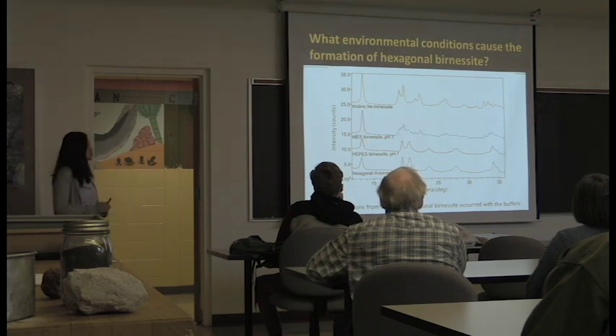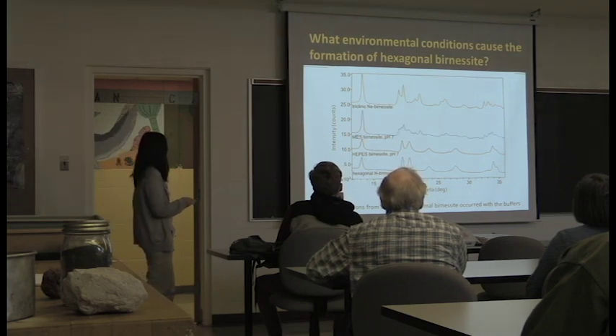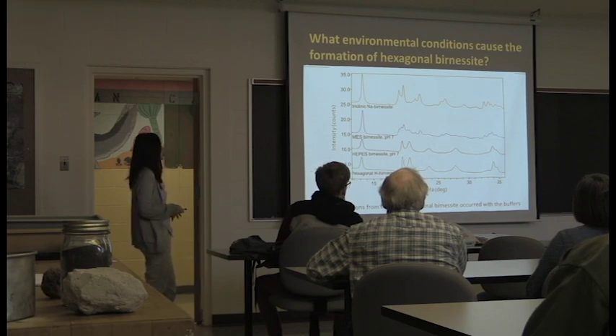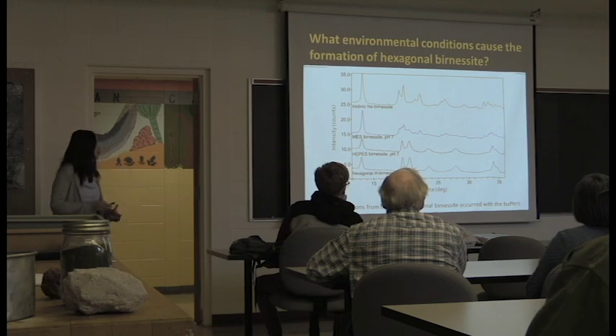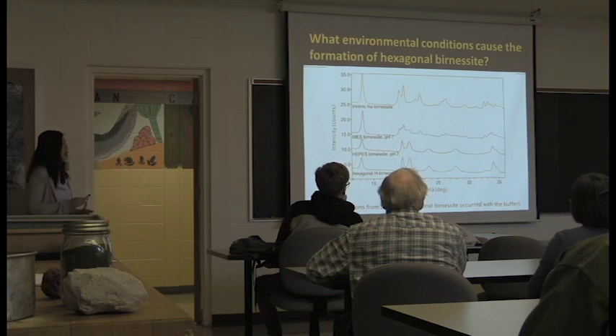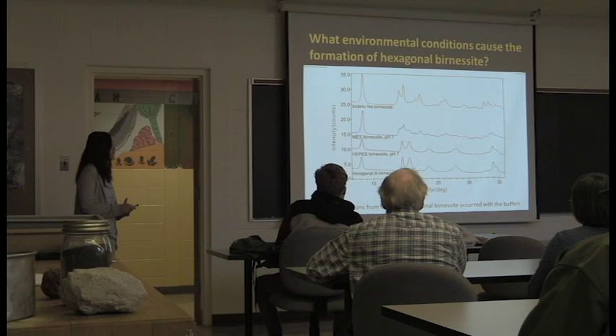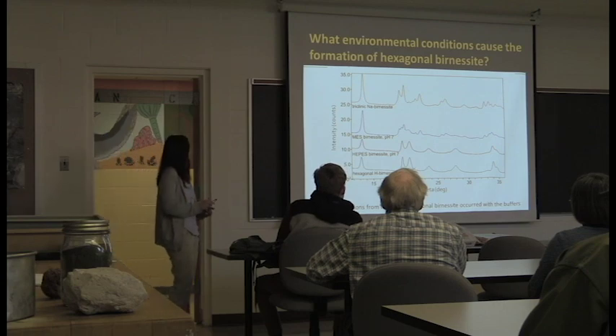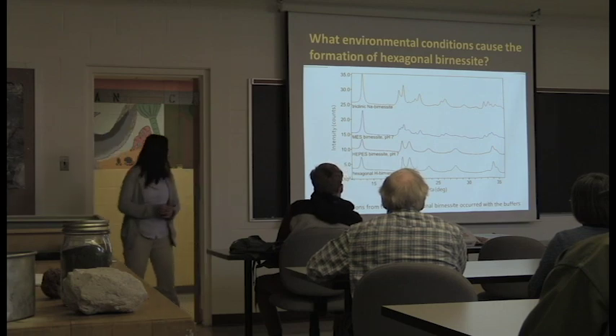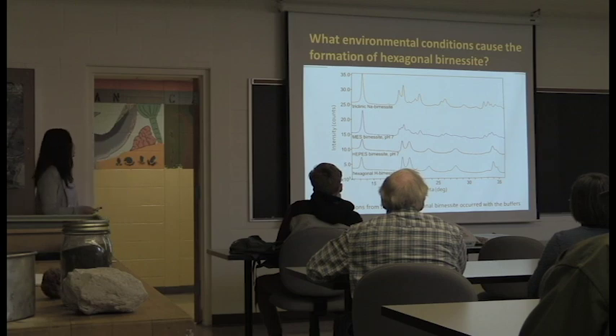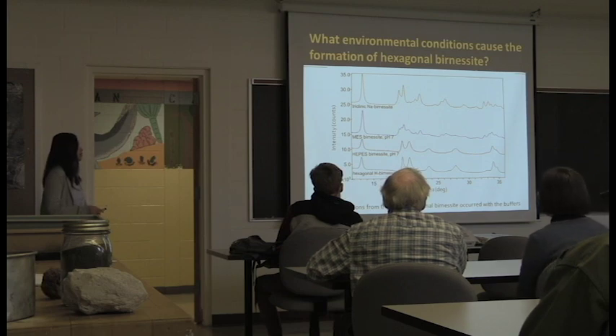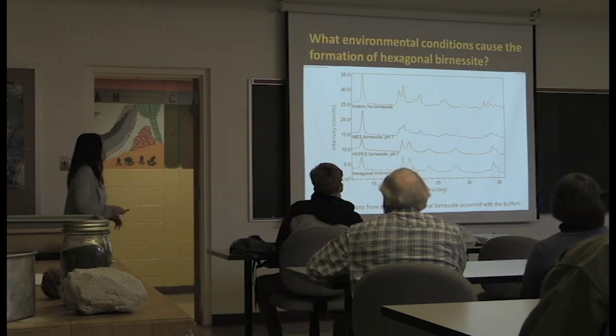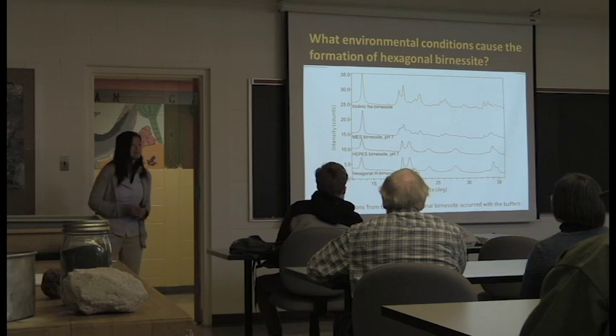When we put it in a different buffer, an MES buffer, we also see some changes in this region. But it's not a full hexagonal birnessite. It's actually a mixture between the two. But the point is that we're seeing these transformations from triclinic to hexagonal birnessite in these laboratory buffered experiments. The reason why it turns out that the MES buffer is not as strong in producing hexagonal birnessite is because MES has a weaker buffering capacity at pH 7.